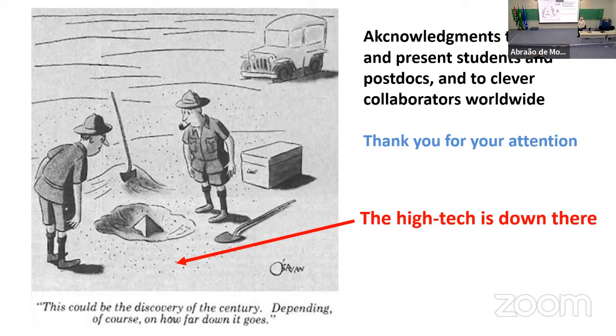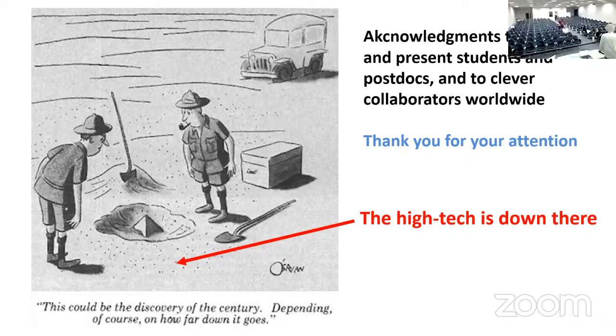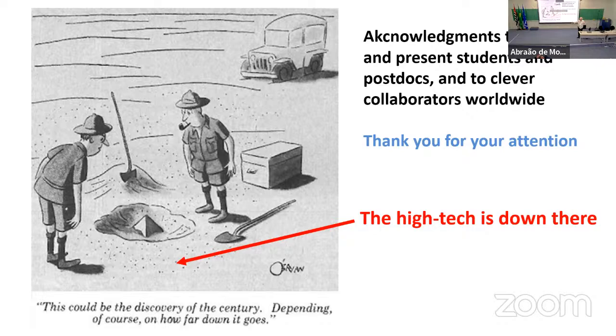Hi, about the CO2 storage, how stable is the CO2 if it stays inside? I think I forgot to say that. We need to get the CO2 in at room temperature. We need moderate pressures, like I would say 3 to 5 bars. If you keep the pressure, the CO2 stays in there. If we lower the temperature, not much, below zero, the CO2 will stay. So that's why it's an interesting case for actually capturing CO2 in a gas stream. You capture the CO2, let's say the hydrogen goes through because you want it. Then you can empty the column, pump the CO2 into the ground and reuse the column indefinitely because this is a reversible process. That's what we have found.